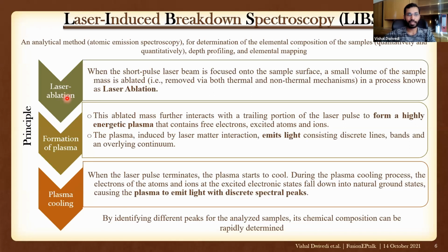So firstly, laser ablation. When the short pulse laser beam is focused on the surface of the sample, a small volume of the sample mass is ablated, and this process is known as laser ablation. After that, there will be formation of plasma. This ablated mass further interacts with the trailing portion of the laser pulse to form a highly energetic plasma that contains free electrons, excited atoms, and ions. The plasma induced by laser-matter interaction emits light, which consists of discrete lines, bands, and an overlying continuum.